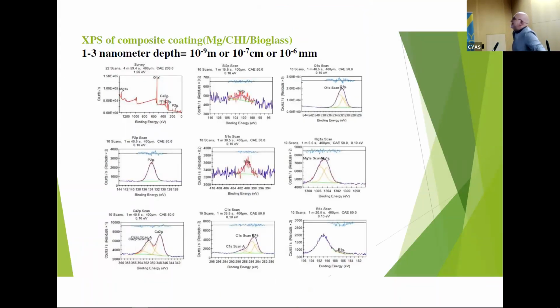And that's XPS. XPS is just for the surface. If you want to make any analysis of the surface, you have to use XPS. You have this coat, and we have to know what kinds of material I have. Calcium, okay. Phosphorus, okay. What do I have again? Boron, do I have nitrogen, whatever. XPS makes the analysis of the surface. The analysis of the surface is just between 1 and 3 nanometers, which means 10 to the power minus 6 millimeter. This beam goes exactly that deep to make the analysis of the surface. And that gives you an indication of what you have exactly on the surface, with all the compositions, the percentage, and the quantity of each element present in your coat.